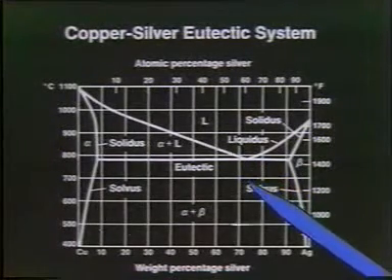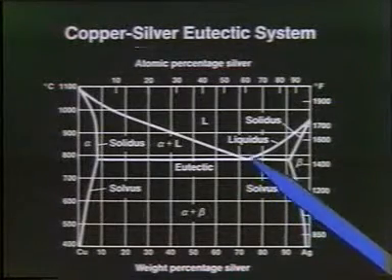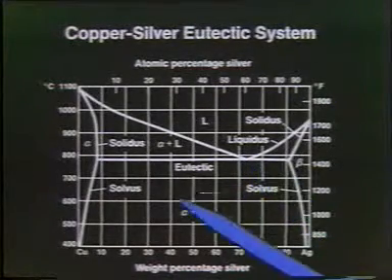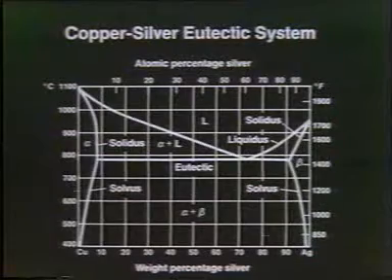Wouldn't it be nice to crawl into this pot of metal and see what's going on as that material solidifies these two different phases? Here's what you'd find out: there'd be a moving solid wall advancing into the liquid, but that solid wall would be like a bunch of fingers — copper or alpha phase on one side, then a beta phase, then alpha, then beta, alternating like sheets of material growing. If you polish and etch it, it will look like a thumbprint structure.